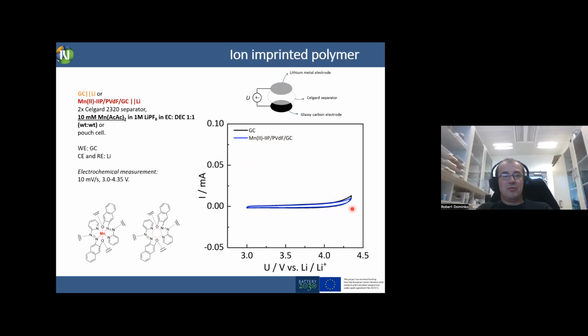But then we move to the electrolyte, which contains manganese dissolved inside. And if we put that against glassy carbon, this orange dotted curve, we see the classical two redox peaks, which are coming from manganese 2 to 3 to 4, and 4 to 3 and 3 to 2 plus reduction and then oxidation.